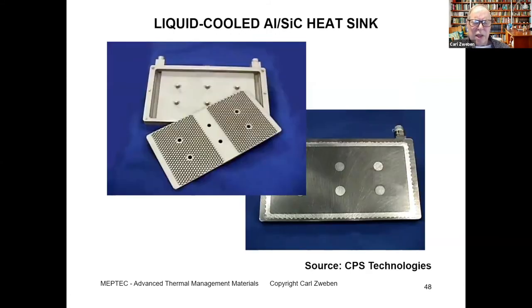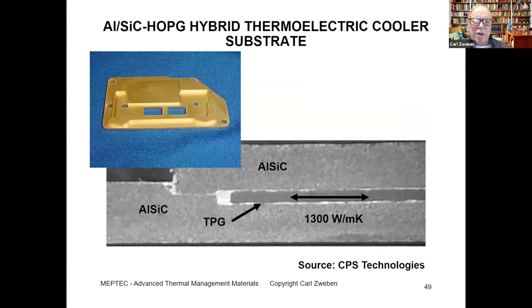So here's an example of a liquid-cooled heat sink made by CPS Technologies. And again, this is an ALSIC material. We can combine advanced materials the way I showed you earlier, combining highly oriented pyrolytic graphite with monolithic aluminum in a complex enclosure. Here we have ALSIC combined with highly oriented pyrolytic graphite in a pedestal. And if we look at the bottom, it's a cross section, and TPG is a trademark for thermal pyrolytic graphite, which is one form of highly oriented pyrolytic graphite. So we're taking advantage of this heat spreading ability of the material combined with the low CTE of the ALSIC package.